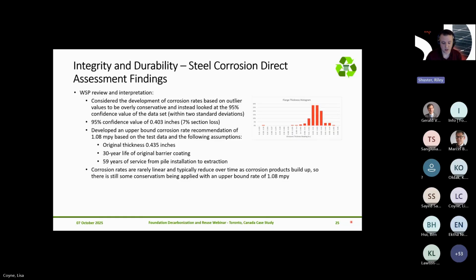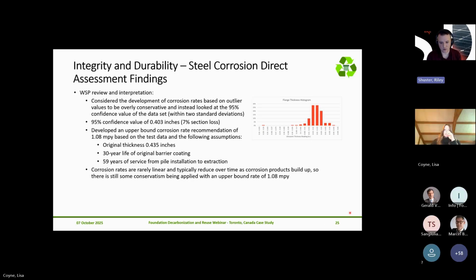Based on our experience and review of literature, we would not expect the corrosion rates to be linear. So they typically will reduce over time as you get corrosion products that build up at the boundary. And so by specifying a linear rate here, we still do have some conservatism, but we note that our approach is more in line with the expected values that come from the Caltrans guidelines.